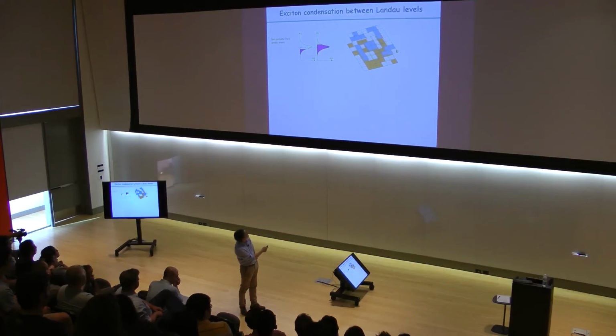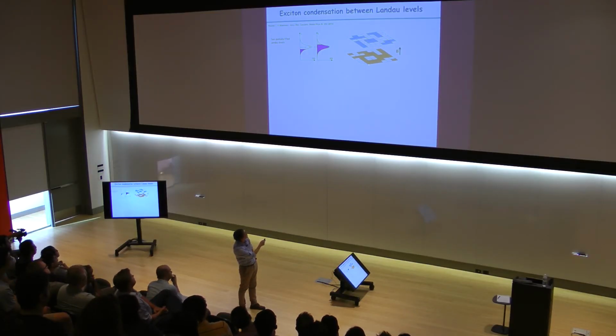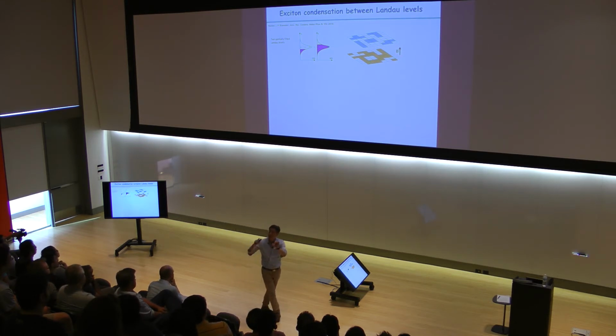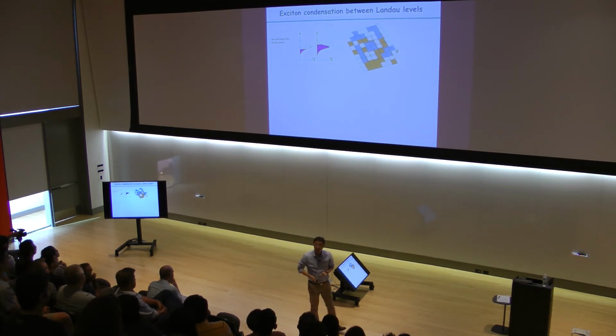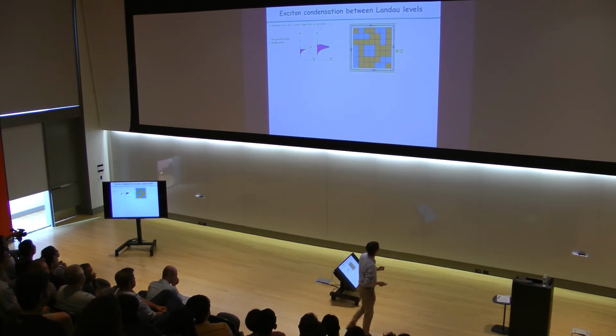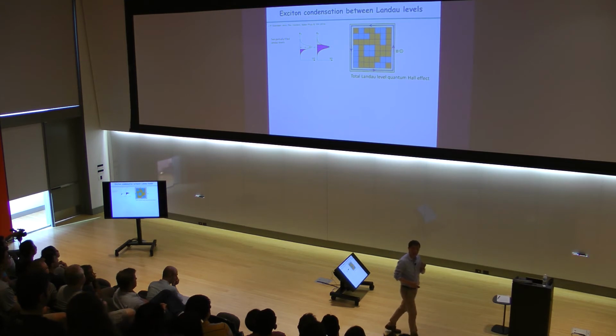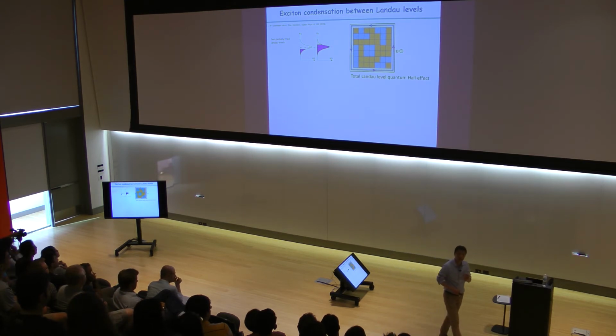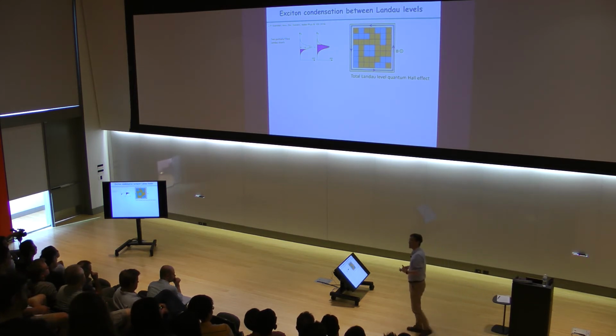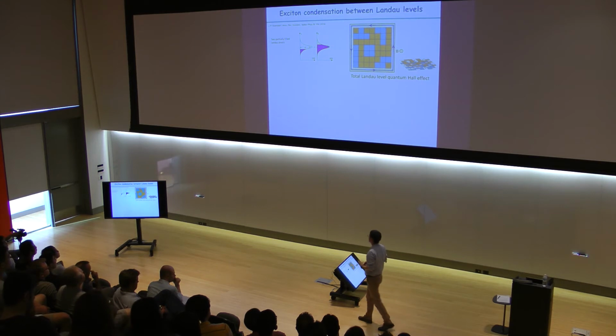If you just go back to this picture, basically here's the electron directly related to the hole, and the electron directly related to the hole, such that you start to see that these exciton pairs actually form in this picture, right? But as a whole, this is a full Landau level, which means that as a whole, they actually restore the quantum Hall effect, as if these two layers behave as one layer, right? And these beautiful arguments were actually worked out already in gallium arsenide.